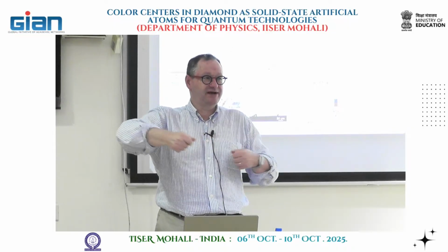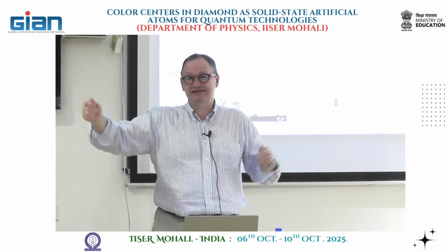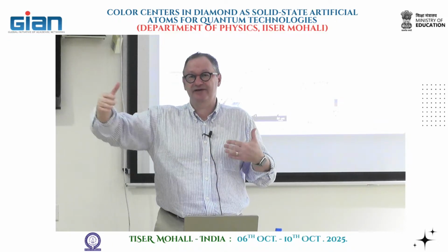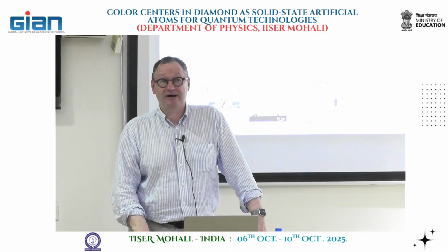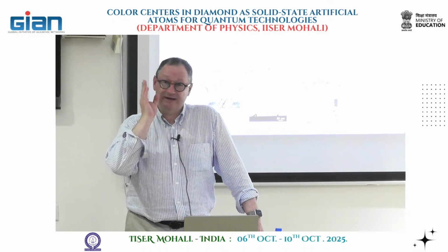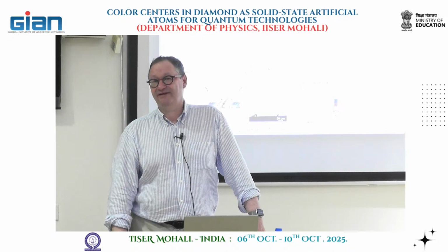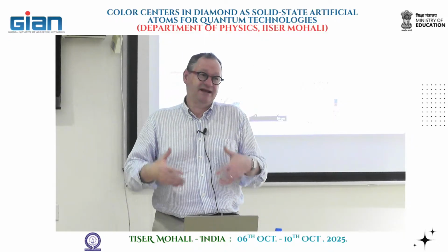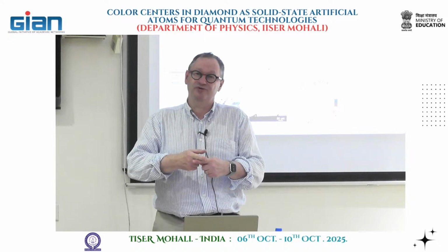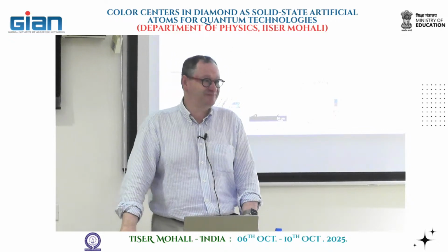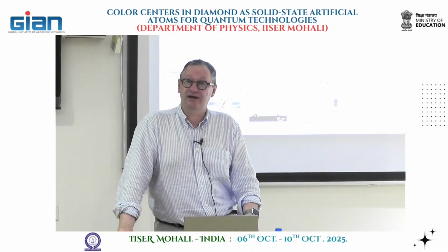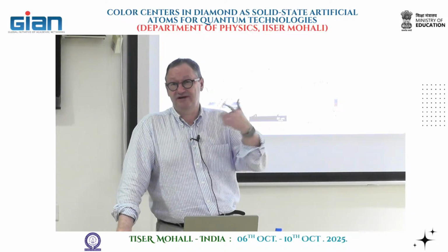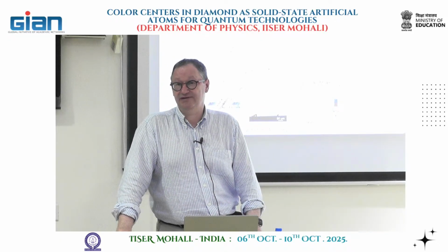You keep the symmetry, and then you can go up to the Tesla range, 0.5 Tesla. What you need is to accommodate for the frequency getting higher and higher. But apart from that, as soon as your magnetic field is perfectly aligned, there's no problem. You keep the good basis states. Now, as soon as there is a transverse component, and this will be discussed in one of the papers I propose for tomorrow, that will mix up the states. And the mixing of the states, of course, will have drastic consequences on the contrast of the magnetic resonance.